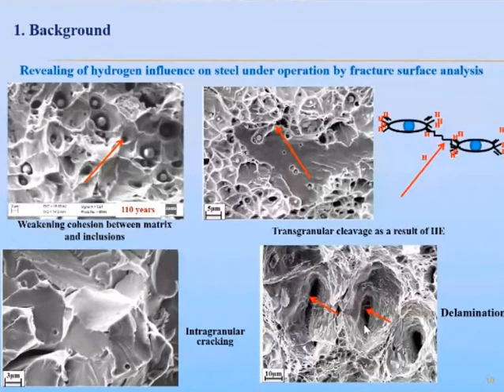It is interesting to consider the mechanism of fracture and energy consumption of fracture in areas between these decohesion elements. If a fracture is ductile with more energy consumption, then fracture realizes due to micro-void coalescence, and a role of hydrogen can consist in formation of high pressure in voids. However, these decohesion elements can also be fractured in a brittle manner, usually by cleavage.